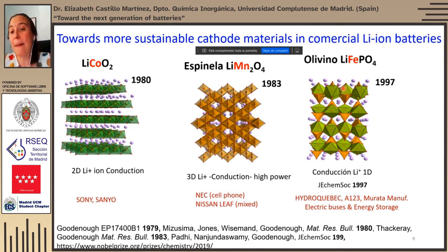On the other hand, the even more friendly lithium iron phosphate, which was also developed by the group of Professor Goodenough, but this time at the University of Texas at Austin, has an olivine-type structure where only one-dimensional tunnels for lithium-ion diffusion are there. This imposes some more limitations on the material, both ionic and electronic conductivity, but this can be overcome by properly nanostructuring the particles so that the tunnels where the lithium ions have to diffuse are along the short direction in platelet-like particles, and also by carbon coating the nanoparticles.